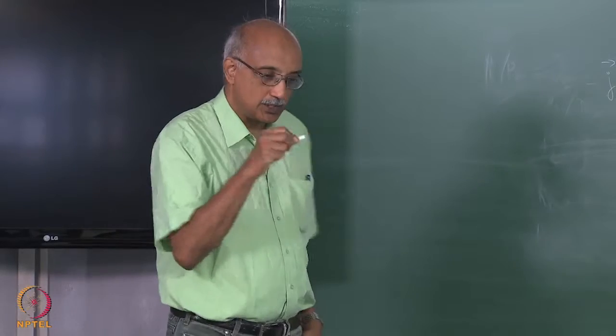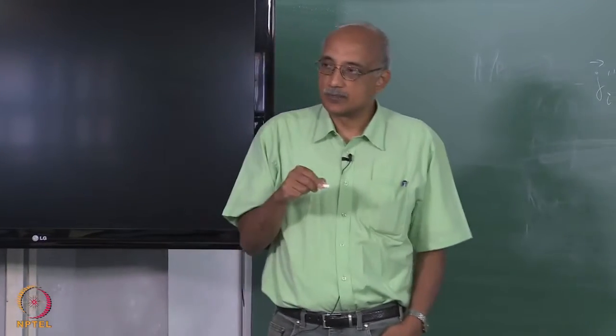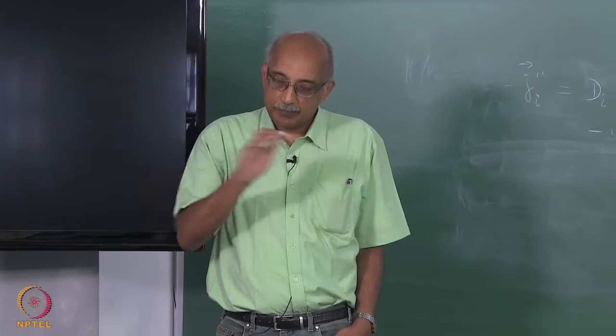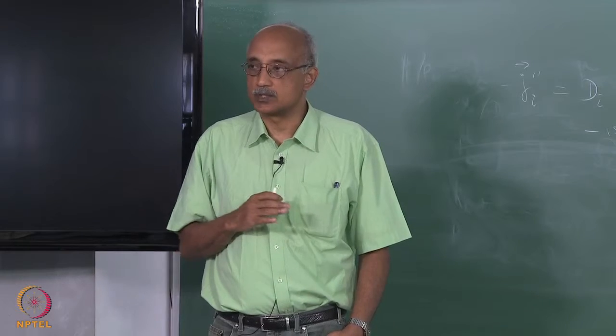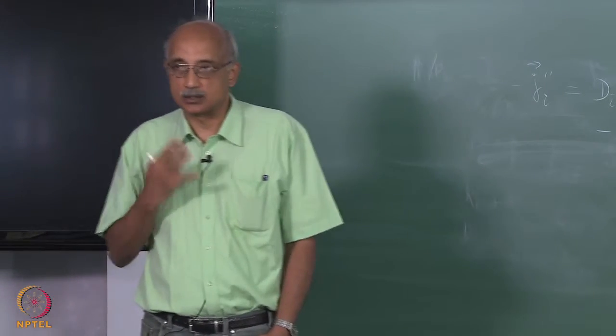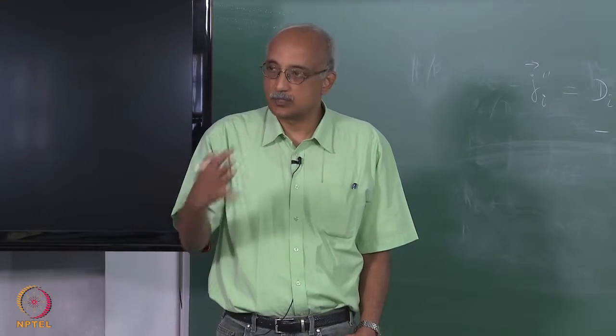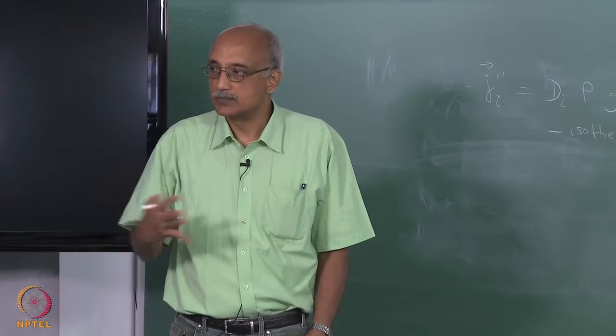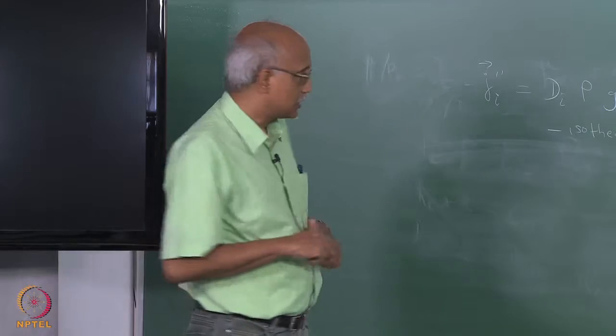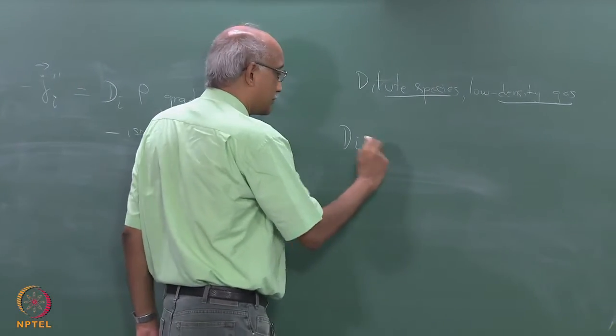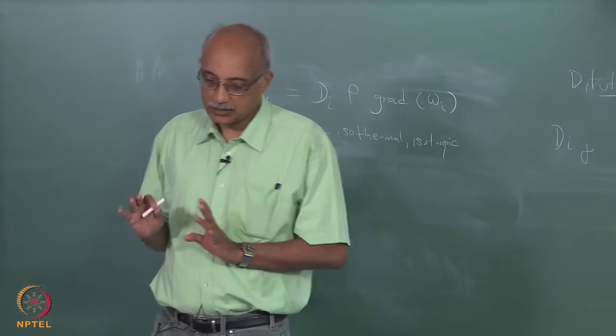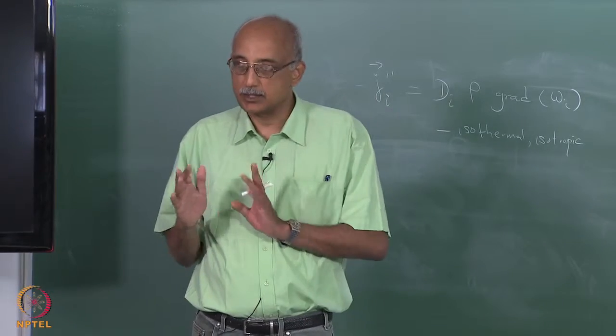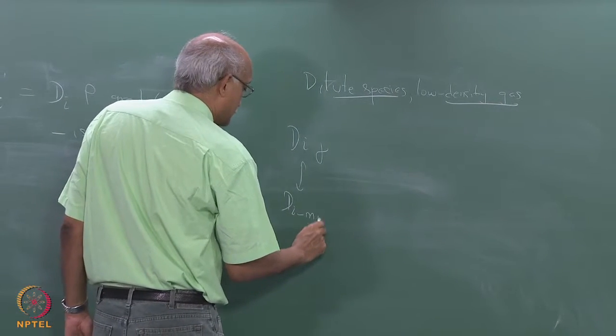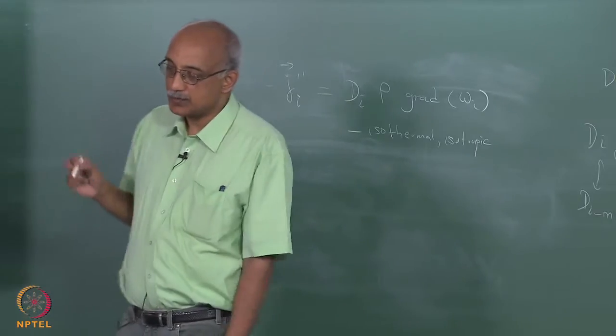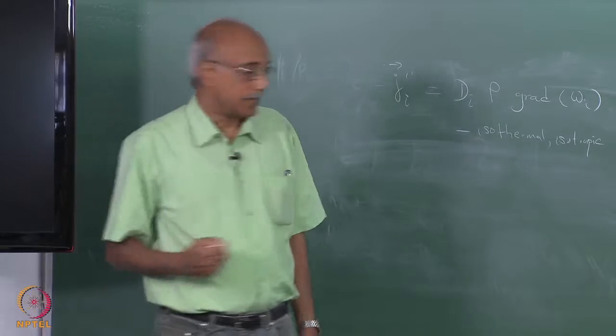In other words, as these dilute species move around, they are going to be encountering other molecules that are present in the system. And each binary encounter imposes a certain diffusion coefficient, because the diffusion coefficient is basically something that reflects random walk. A random walk is basically the distance that is covered between one collision to the next. And so, you can essentially estimate a binary diffusion coefficient D_ij, which simply reflects the diffusion path associated with binary collisions. And from this, you can estimate D_i,mix, that is the diffusion coefficient of species i in a mixture of gases rather than in a binary system.